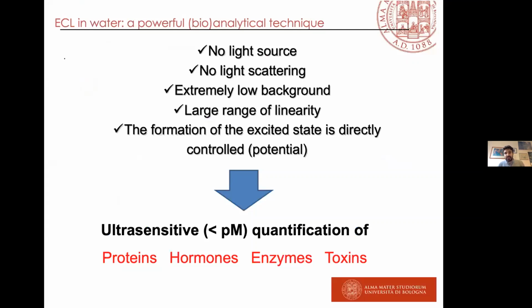the chemiluminescence, so very high signal-to-noise ratio, because you don't have an excitation source, you don't have light scattering from the excitation source. This allows you to have very low background and very good signal-to-noise ratio. This is also due to the fact that the emission is localized only on the electrode surface, and the potential controls the emission. So you can decide when to apply the potential, with a very high signal-to-noise ratio.